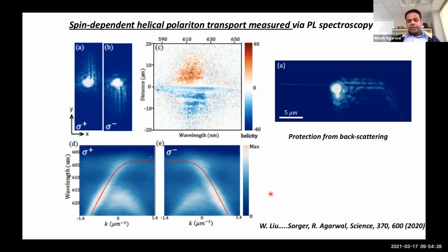Since these are topological polaritons, the idea is, can they navigate a very sharp turn without backscattering? Clearly they're not backscattering, but can they also navigate a very sharp turn? We created the zigzag interface mode with a very sharp, 120-degree turn, and clearly they can navigate this turn without backscattering. And these are polaritons, not photons. All these things are very interesting, because what we've created are polaritons with spin-dependent properties and a protection from backscattering. So the loss mechanism further decreases.